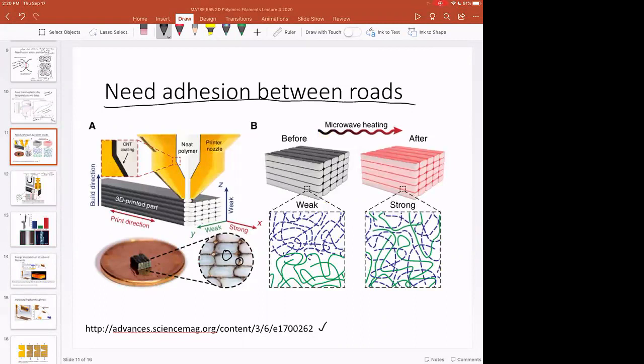And so it's not the carbon nanotubes that are doing the adhesion. This diagram is great because it's saying weak adhesion before microwave heating and strong adhesion after. These are interdiffusion of polymer chains, which makes the part strong. We know that now. And so what the microwave heating does is that the microwave acts on CNTs and causes heating at the interface.